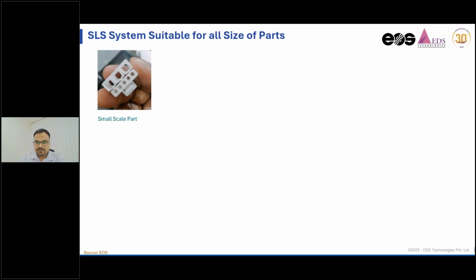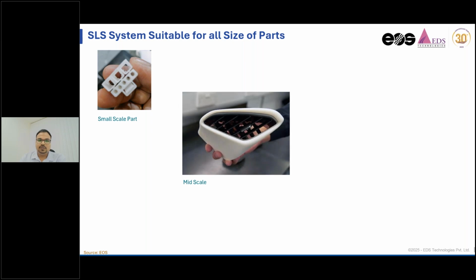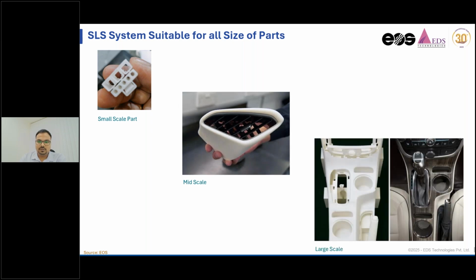So SLS is actually driven by a laser. The laser is the heart of the process, and the laser spot size is in the range of 500 microns. It is able to produce very detailed geometry, starting from 0.6, 0.7 mm of the polymer component. You can print whether your component is a small scale part, a mid scale part, or a large scale injection molded part; all of the parts can be printed using the SLS process.